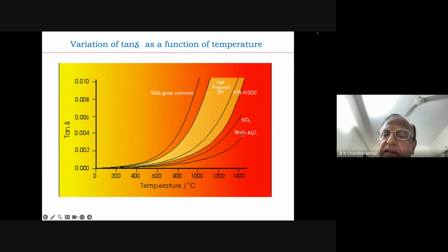Compared to 99% alumina, if you look at 97% alumina, it has got some other components, the 2%, which has a better microwave interaction even at lower temperature. So depending upon the composition, the interaction temperature varies.